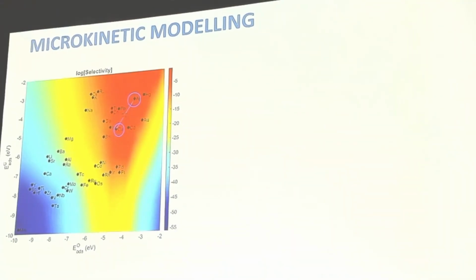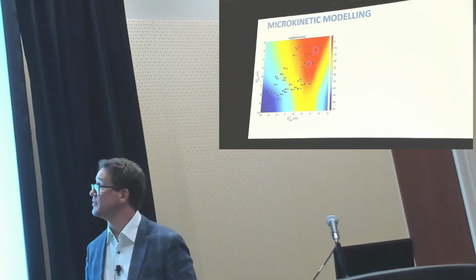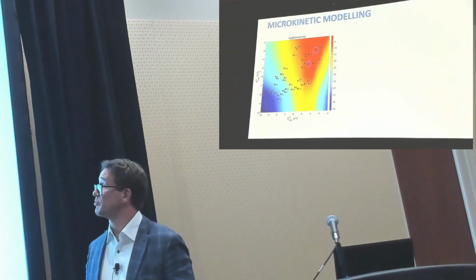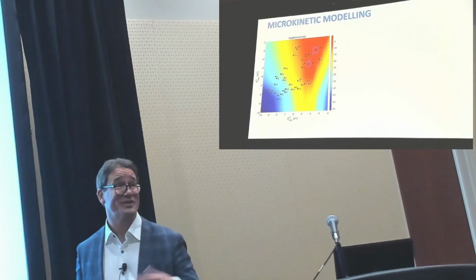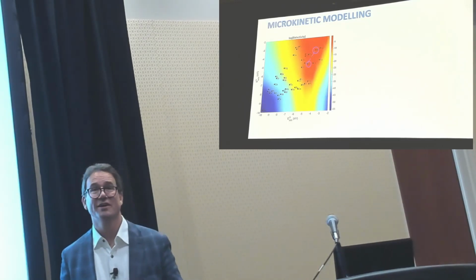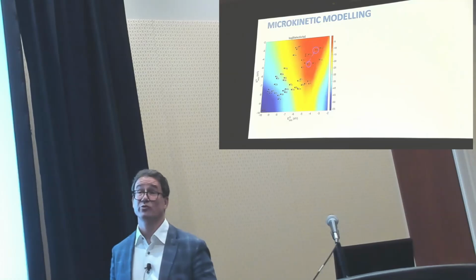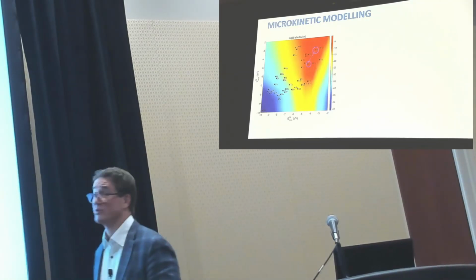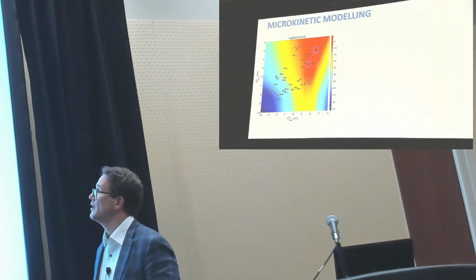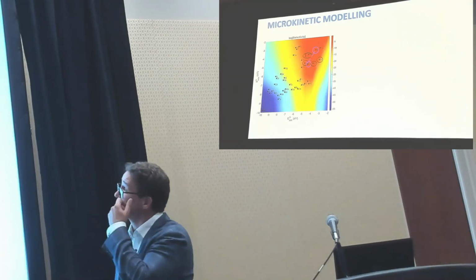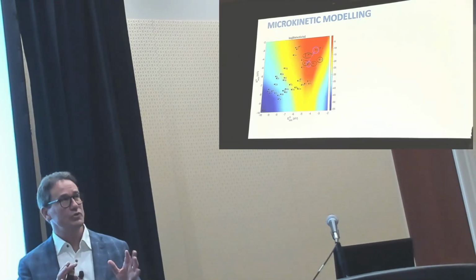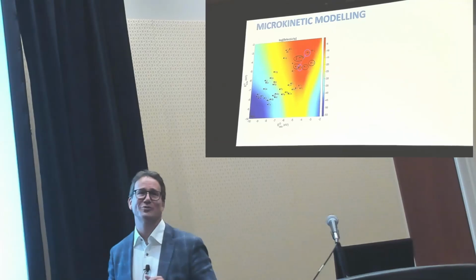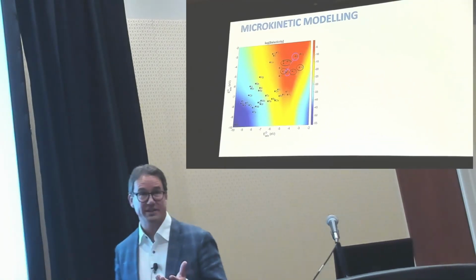And then you have a number of most reactive metals that are not really going to play a role in this reaction. It should be admitted that we are probably doing a lot wrong here because they should probably oxidize like crazy. But since they are sort of off the volcano top anyway, we don't care so much that we are missing some physics there. But there are a number of different elements here that we see are close to silver. So why not try to see if we can use those in more detail?